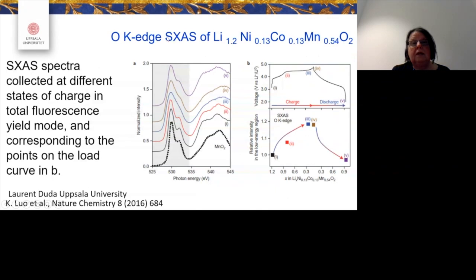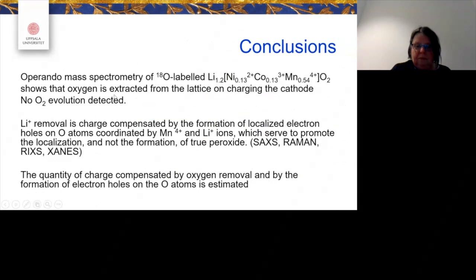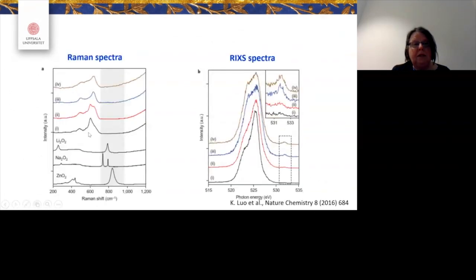So by again using SAXS and RIXS and Raman and XANES and all kinds of methods, and following this charge curve, especially the first cycle, the first charge, we can see that we do have this oxygen reaction. There is something happening here. Raman spectra also show that there is an oxygen reaction, and here in the RIXS we could also see that a lot of defects formed in the oxide lattice, in the bulk structure.